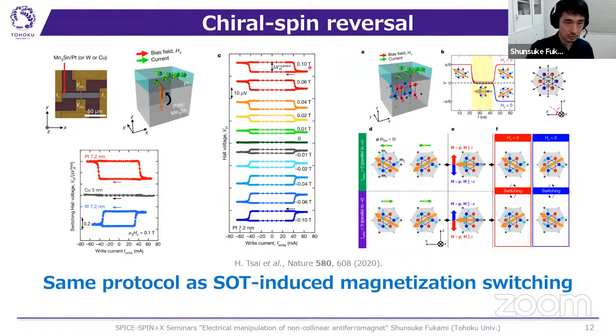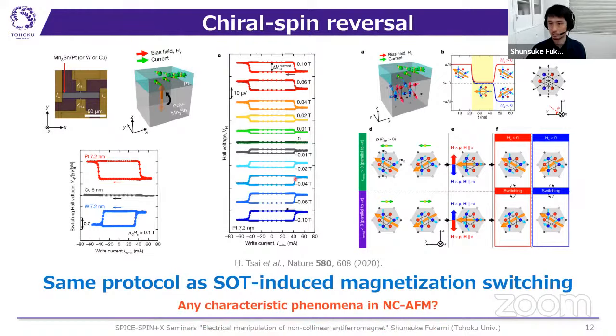And they also studied the external field H_x dependence. As you can see, the switching direction becomes opposite by changing the sign of the external field. So this is very similar to the spin orbit torque-induced magnetization switching, and they give theoretical discussions, and according to the explanations, the octupole moment behaves like the magnetization in the ferromagnet, and the octupole moment switches with the same protocol as the spin orbit torque-induced magnetization switching. So this is very similar to the ferromagnetic systems.